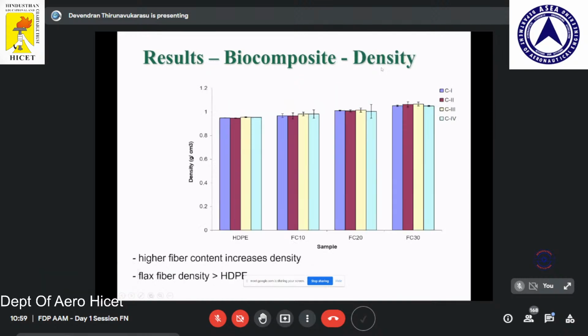So this is the density. The same thing here: if you increase the fiber content, the density keeps increasing. We optimized the fiber content, so we go up to 30%. If you go to 50%, the material becomes very brittle and the mechanical properties are not good. In other slides, I will explain how the mechanical properties change. The flax fiber density is greater than high density polyethylene, so if you increase the fiber content, the density increases. That is what we concluded here.